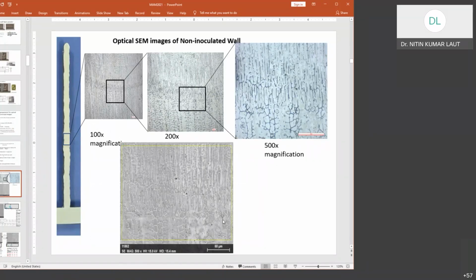Now if you see the same image specifically at higher magnification, you will find very smooth distribution of these grains, without any major defects we have discussed, like porosity, cracking, bulging. We could hardly get that even in these characterized images of the specimen. So this image, whatever you are seeing, is at the center location, because we believe that at the start and at the end, these layers are subjected to some outside environment. For example, at the start, they are dependent on the base material, whereas on the other end they are subjected to ambient conditions. So we have taken a moderate area for this analysis, and we are getting pretty good results.